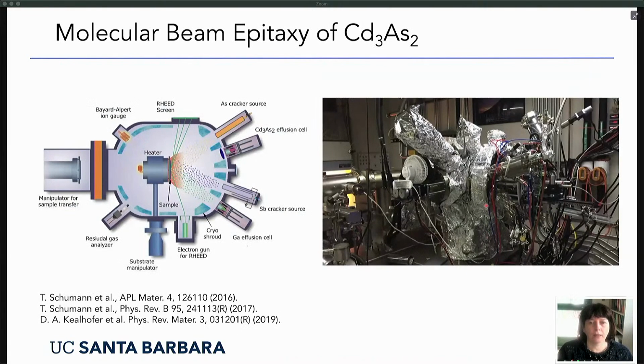And so what we started out with is growing these cadmium arsenide films by molecular beam epitaxy, mostly for the usual arguments. MBE is a technique where you get high purity films. It's a low energetic deposition technique, and we expect to synthesize fairly high mobility films with that technique. So the way we grow it is on 3-5 semiconductor layers, which I will show you in a minute. And we simply evaporate the compound itself, cadmium arsenide. Okay, so it looks relatively simple.